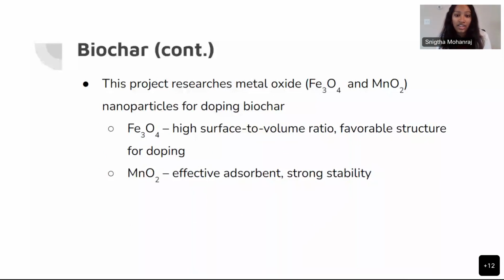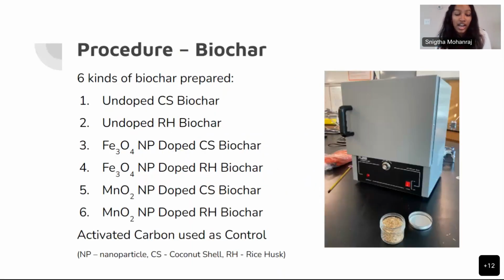And then the manganese dioxide is an effective adsorbent and has a strong stability. So six kinds of biochar were produced. This was undoped coconut shell and rice husk biochars, iron oxide nanoparticle doped coconut shell and rice husk biochars, and then manganese dioxide nanoparticle doped coconut shell and rice husk biochars. And in some of the graphs, you'll see that activated carbon was used as a control just to see a comparison as to how effective these methods are in accordance to the activated carbon, or AC for short.